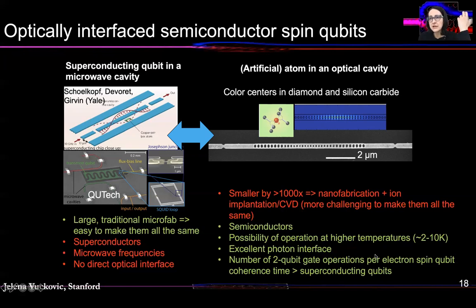Maybe most importantly, the number of two-qubit gate operations, non-trivial operations that you can do per electron spin qubit coherence time, is much greater than for these superconducting qubits, which means that eventually you should be able to build larger depth quantum circuits with this platform. But what is the problem? I mean, there is no free lunch. In this case, you are working with a platform where everything is smaller by several orders of magnitude. You have to use non-standard fabrication methods both to introduce qubits and to fabricate circuits, which is why it's much more challenging to make them all the same, and that has made scaling of these platforms difficult, but not impossible.